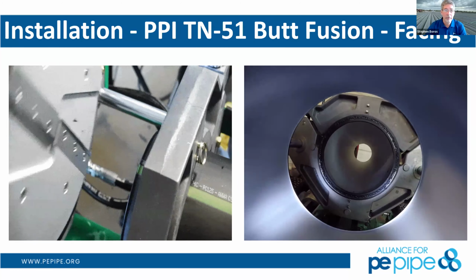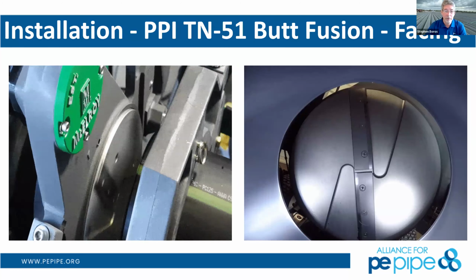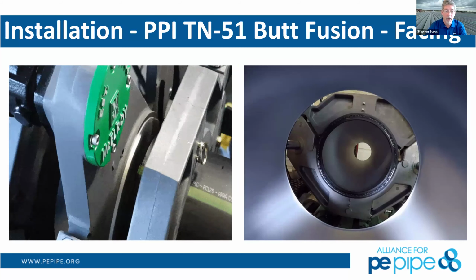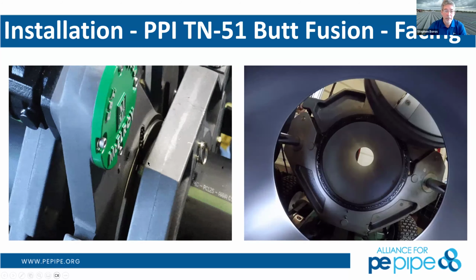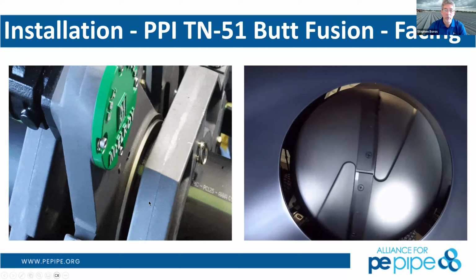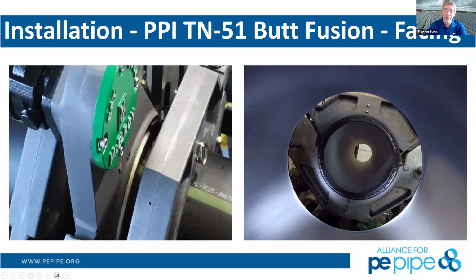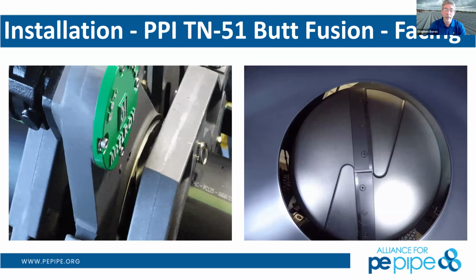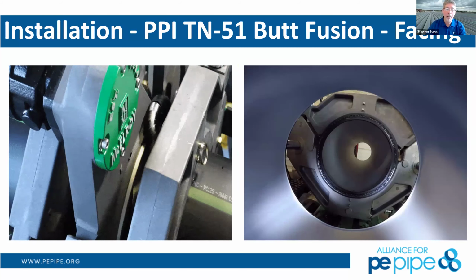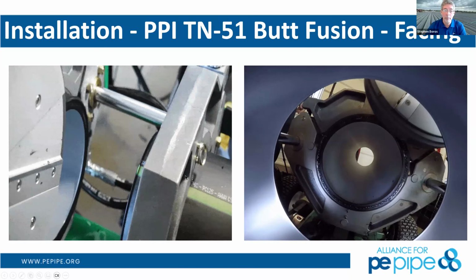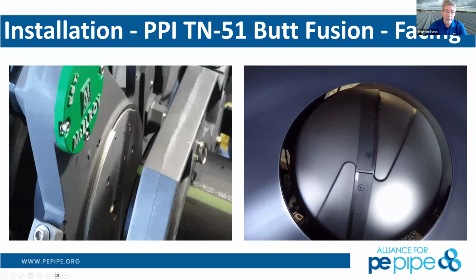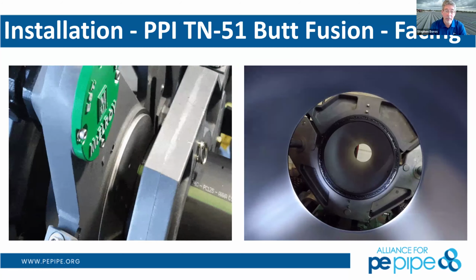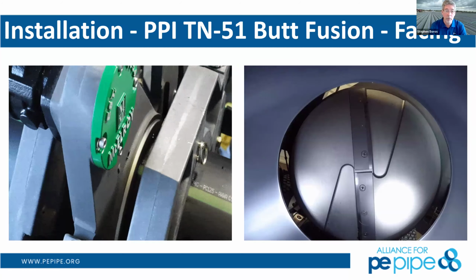So you can see here, the first step of that is to face the ends. You put the pipe into the fusion collets and you bring both ends together, and these blades spin slowly around it. And that gives you nice, clean, uniform, parallel surfaces. So the pipe comes together in a nice uniform manner. So this is the first step in the fusion process, and probably one of the most key parts of it as well.